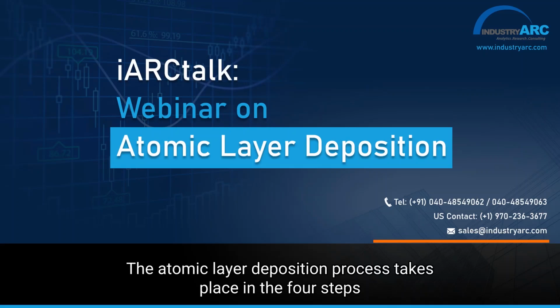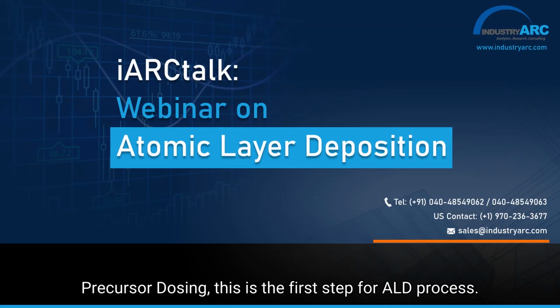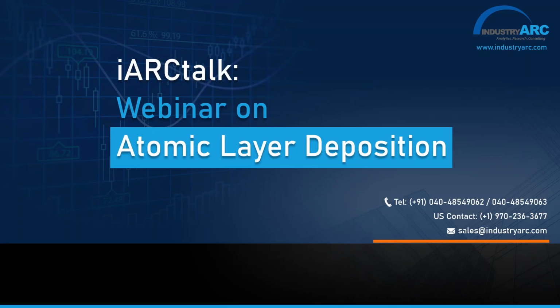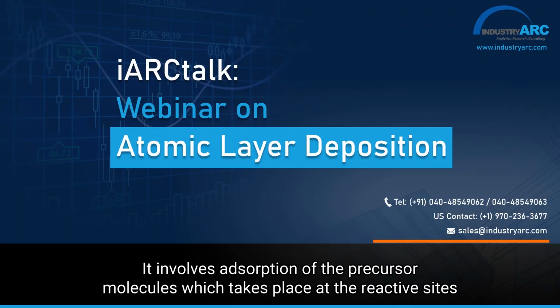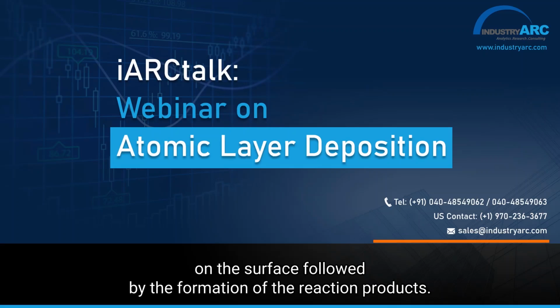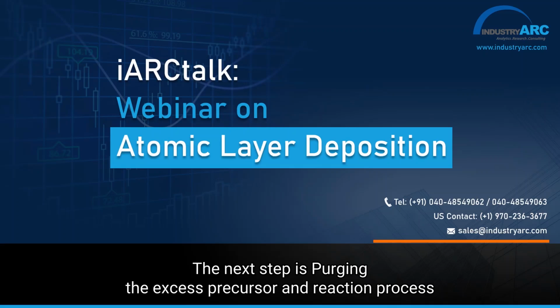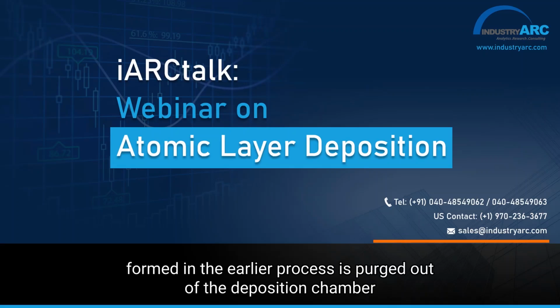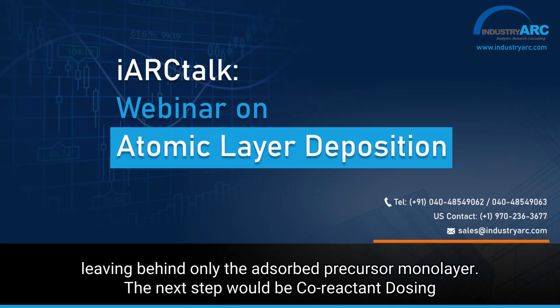The atomic layer deposition process takes place in 4 steps. Precursor dosing. This is the first step for the ALD process. It involves adsorption of the precursor molecules, which takes place at the reactive sites of the surface, followed by the formation of reaction products. The next step is purging. The excess precursor and reaction products formed in the earlier process are purged out of the deposition chamber, leaving behind only the adsorbed precursor monolayer.